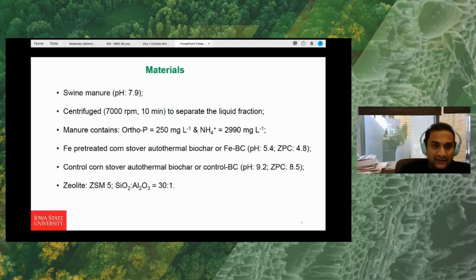So the materials. We have used swine manure with a pH close to 8, and we centrifuged it to separate the liquid fraction. The manure contains around 250 milligram per liter of ortho-P and around 3000 milligram per liter of ammonium nitrogen. We have used 2 different biochars: one is the iron pretreated and another was the iron control biochar. The iron biochar pH was around 5.4 and zero point charge is around 4.8. The control biochar has a pH of around 9.2 and zero point charge is around 8.5. And we have used a ZSM-5 zeolite, which has a silica to aluminum ratio around 30:1.